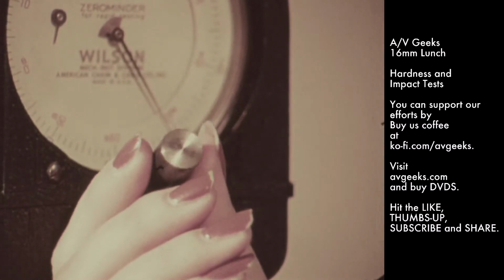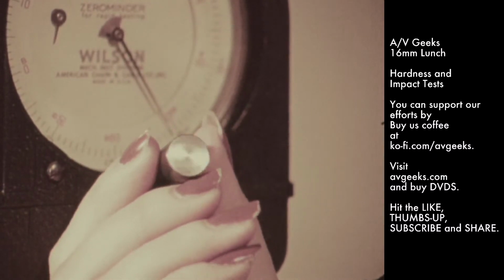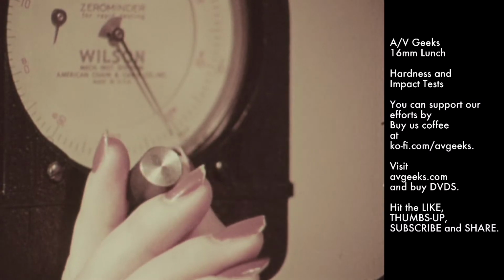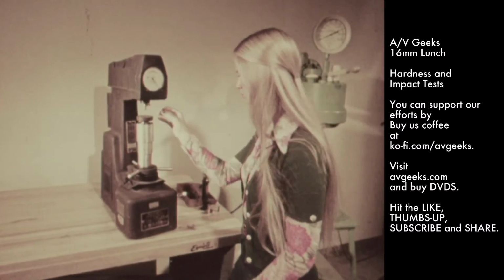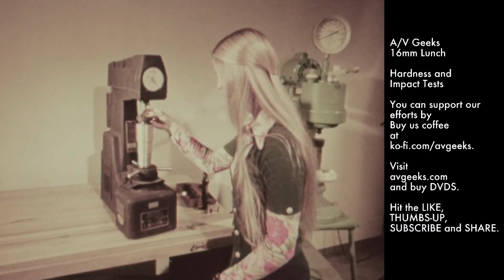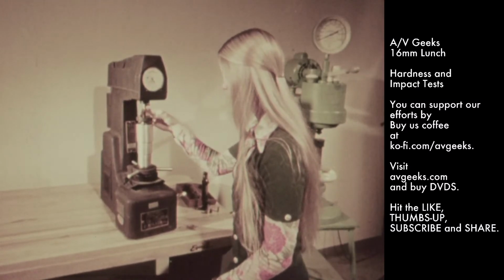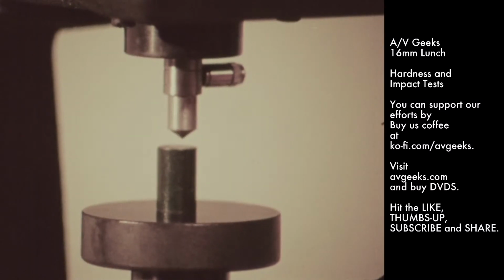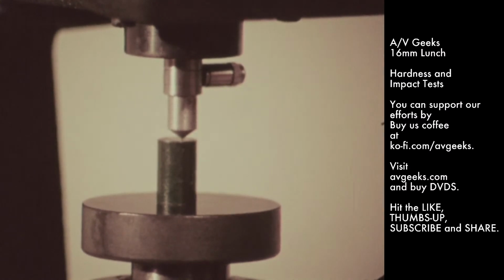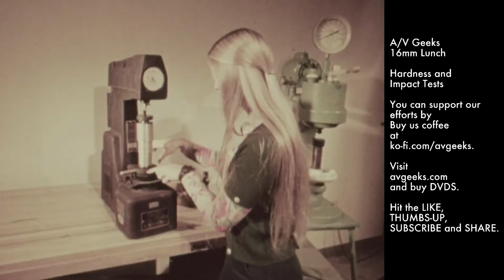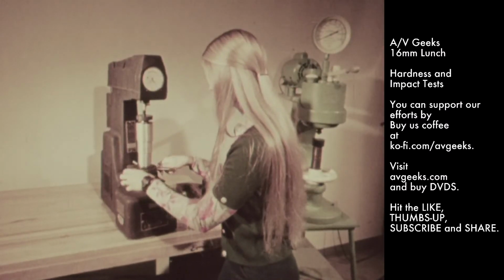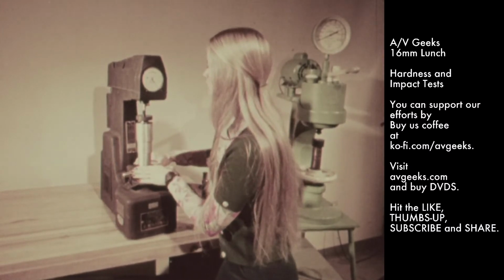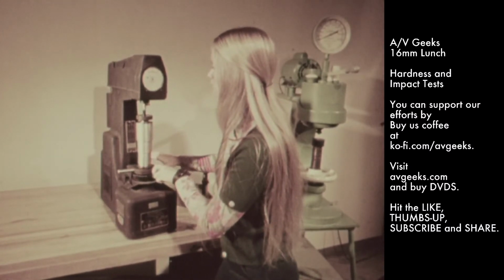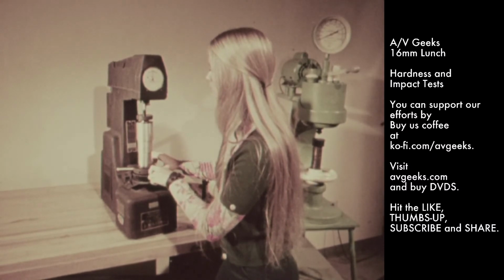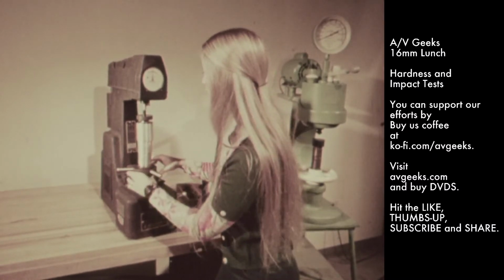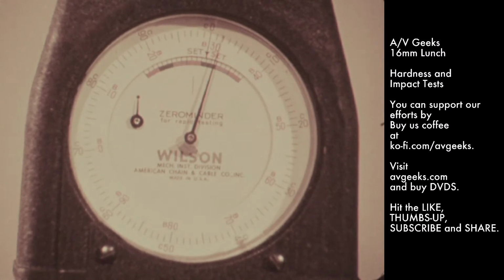A small cylindrical specimen of ASTM 1045 steel with a carbon content of 0.45% will be tested first. The specimen is brought into contact with the penetrator. A 10 kilogram minor load is applied to hold the material and penetrator in contact. This is accomplished by tightening a hand wheel until the dial indicator reaches the set mark.